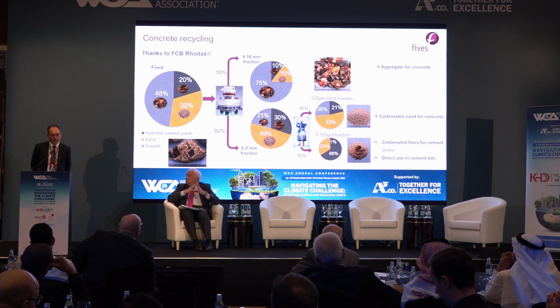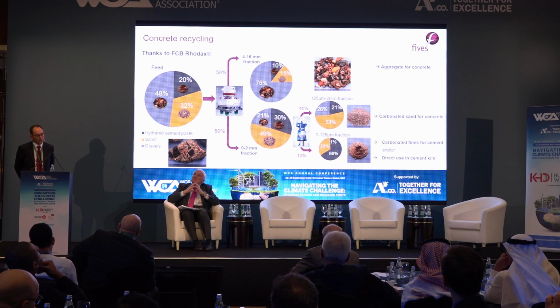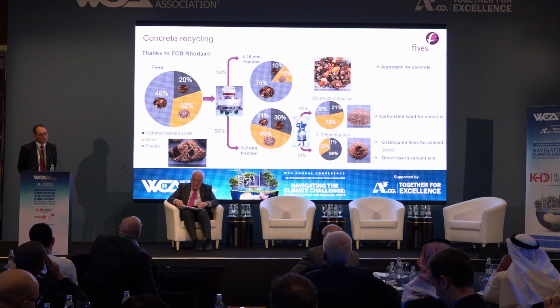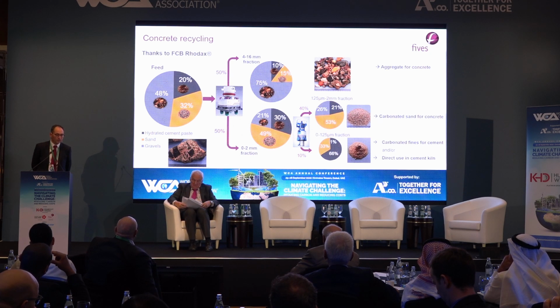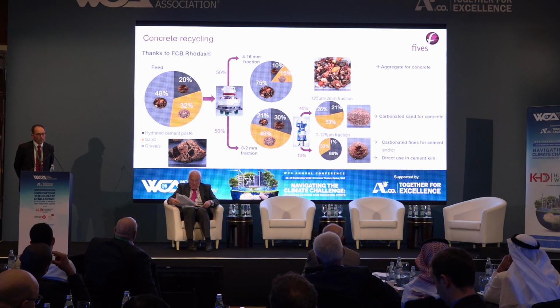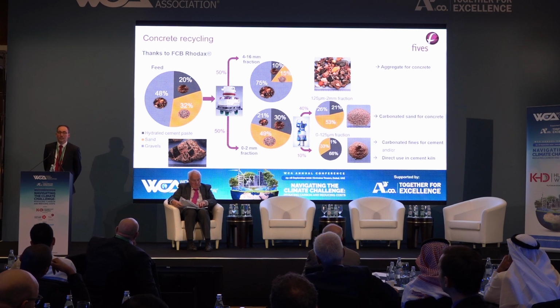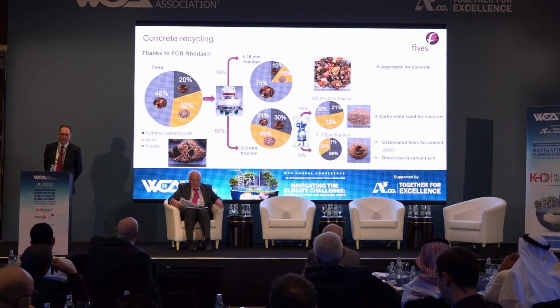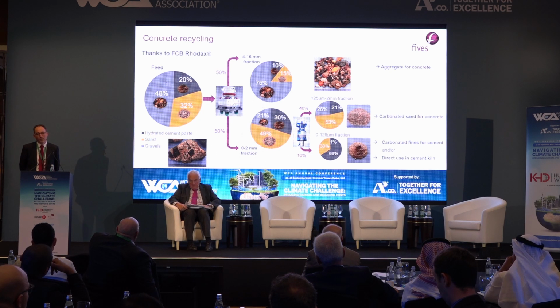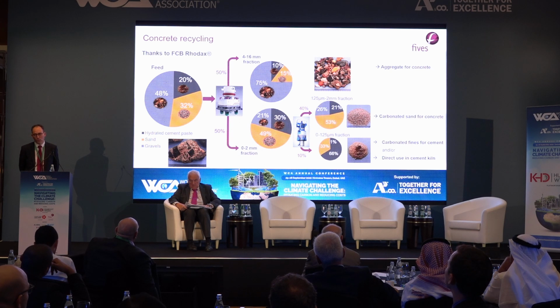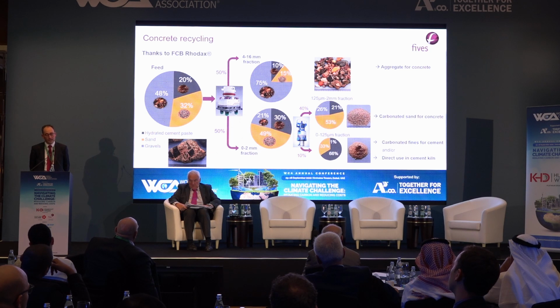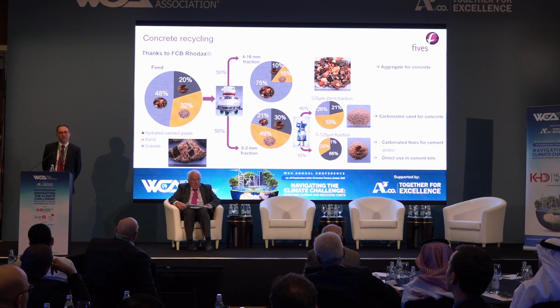but it can be used as well as additive for cement. The benefit is first that the sand, so the 125 micron to 2 millimeters fraction, contains, you see, about 20-25% of cement paste. This cement paste is composed of calcium carbonate that has already released its CO2, but which, put in contact with CO2, will reabsorb the CO2. So this sand is a carbon sink that can be used to absorb part of your CO2 emissions. And the fines, if you put it in your cement, will reabsorb CO2, so it also acts as a carbon sink.